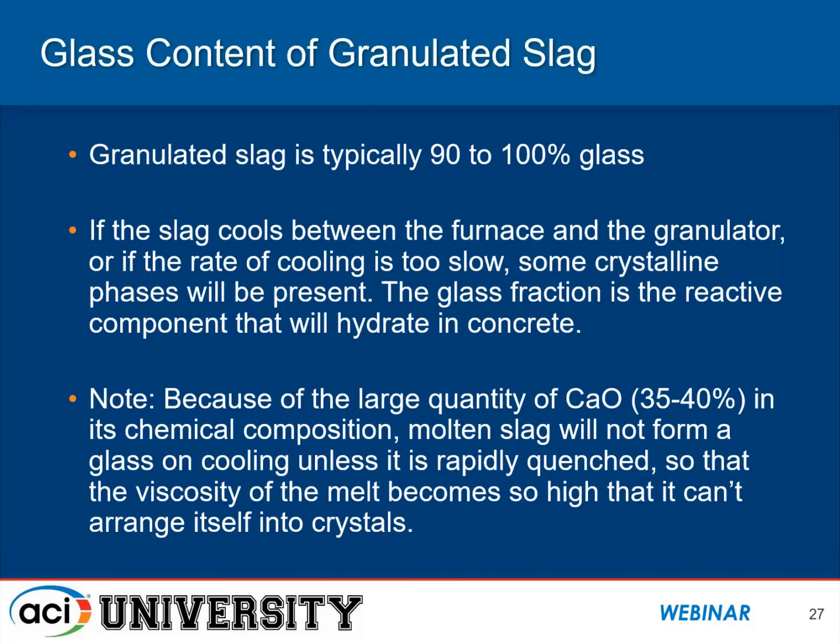I said it's almost all glass, and you may have a bit of crystalline material in it because it depends on how quickly it gets granulated or how much water they're using, but generally it's 90% to 100% glass. It doesn't have to be 100% glass to be very reactive.